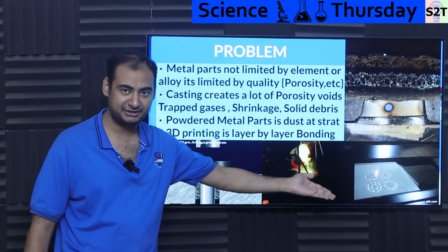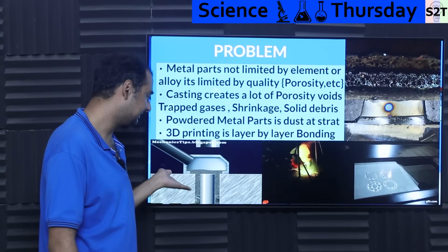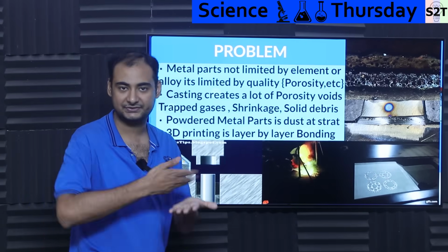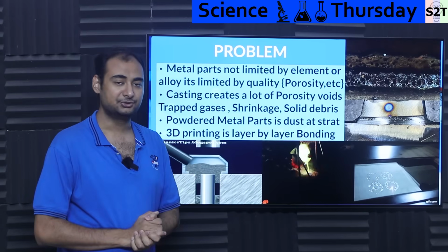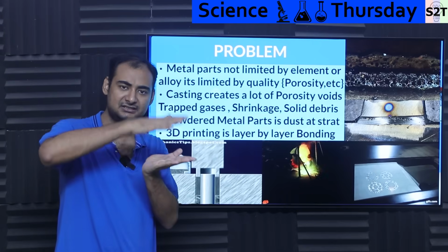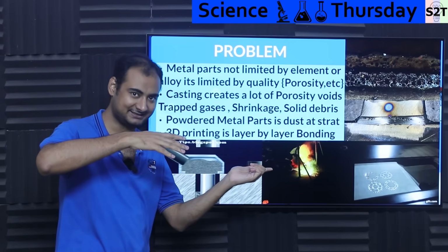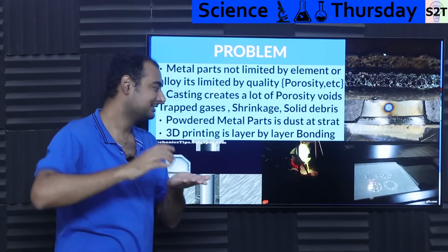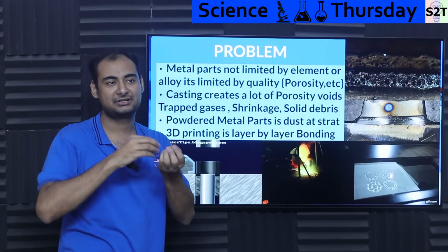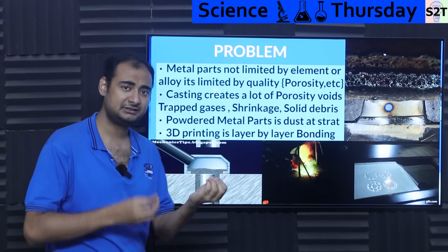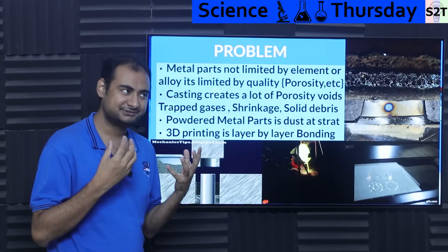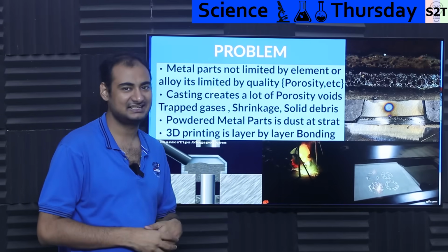And then you come to 3D printing. Inherently the same problem as powdered material. Because you are doing it layer by layer, and you can easily understand that when you're dealing with layers, it's not plastic, it's not one continuous loop. So you have literally every grain boundary that is being molten and then solidified. So grain boundary wise, that's also not that great.